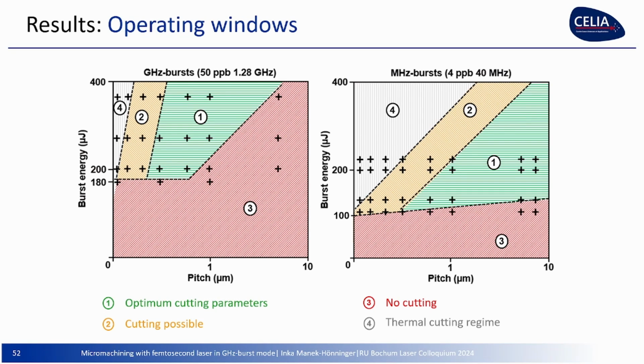Here, just some overview of the operating windows. On the left, gigahertz, on the right, megahertz. Of course, it's soda lime. As you can guess, the green zone is where you have super cutting parameters, super results. The yellow zone is okay, cutting is working, but it's not optimal. The red zone, you have no cutting, it doesn't work at all, nothing happens on your sample. And the gray part is this thermal cutting regime that I showed you, where you have this heat affected zone.